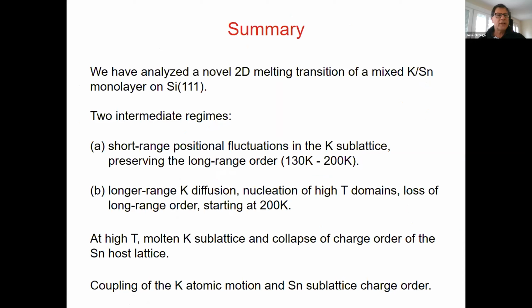potassium and tin monolayer on silicon 111. And we have found that the melting transition goes through two intermediate regimes. The first one is the short-range positional fluctuations in the potassium sublattice that preserve the long-range order, and a second intermediate regime where the potassium diffusion takes place over longer ranges, and this gives rise to the nucleation of high T domains and the starting of losing the long-range order.